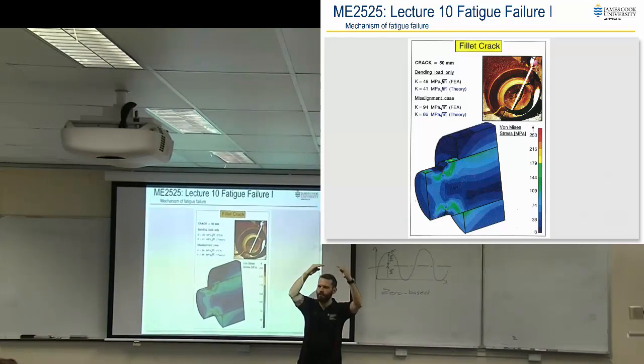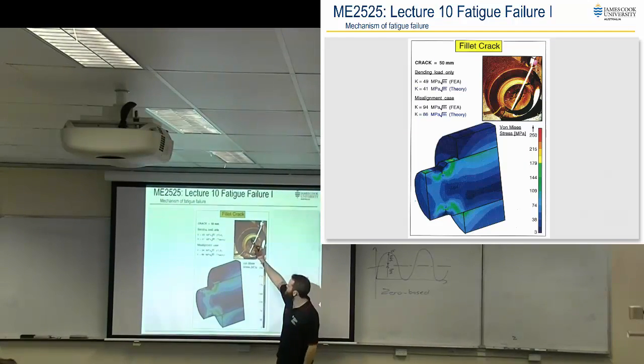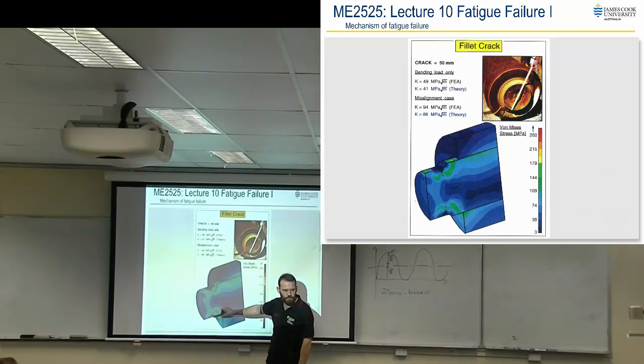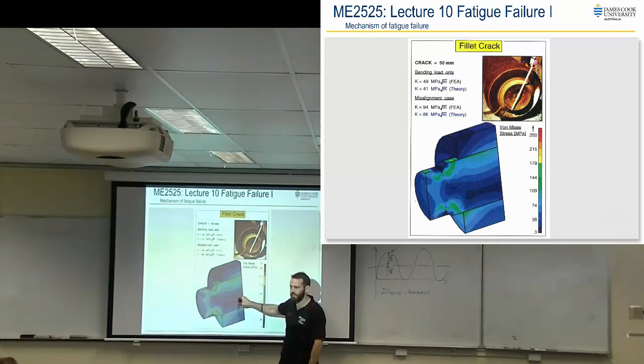So effectively going from tension to compression at each piece of the material. And you can see, this is another diagram of that, there was actually a step in that shaft there. And at the very tip of that stress concentration, that's where the crack started propagating. And this is an FEA model that